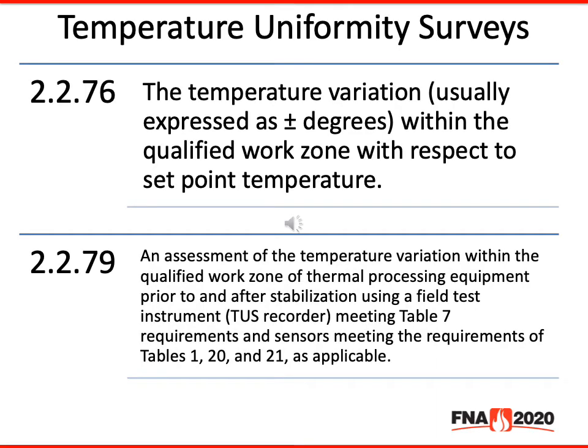Temperature uniformity surveys, in my opinion, is the portion of AMS 2750 that will have the most dramatic effect on product process in a furnace. Let's begin by talking about what a temperature uniformity survey is. In paragraph 2.2.76, it talks about the temperature variation, which is the temperature variation within the qualified work zone with respect to set point temperature. Temperature uniformity survey test is an assessment of the temperature variation within the qualified work zone of thermal processing equipment prior to and after stabilization.